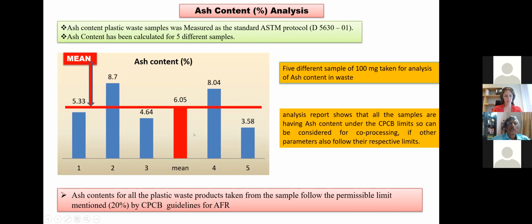So the next slide is ash content. Ash content has been tested in a similar fashion, and it is observed that the mean value of the ash content is 6.05%, which also falls under the guidelines of CPCB and can be considered as an AFR.